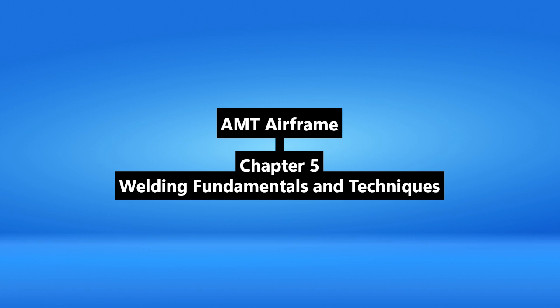Use a soft, neutral flame. Oxidizing flame bad, carburizing flame also bad, increases hardenability. Use the right 4130 filler rod. For critical structural welds, post-weld heat treatment is often required. TIG might be better for thick 4130, but still needs heat treatment.